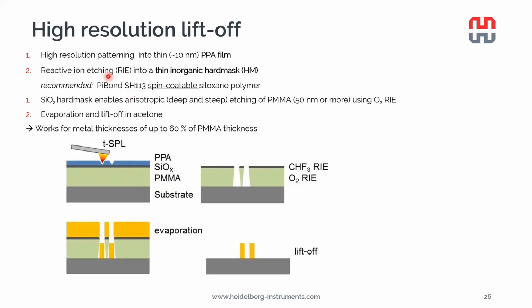So we developed together with the company PiBond a material we call SH113. It's basically a spin coatable siloxane polymer that is reduced into a silicon dioxide when it's exposed to a gentle oxygen plasma, and it forms an extremely thin layer of silicon oxide, which is pinhole free and extremely smooth, only 1.5 nanometers thick. And on top of that, we spin coat PPA, about 10 nanometers typically.